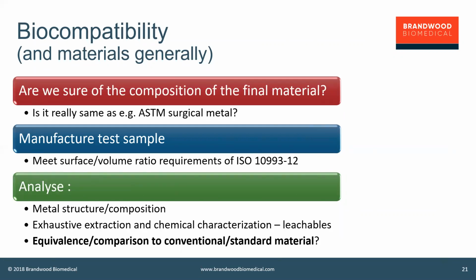And then you will take the solvent residue, analyze it and see what's in there, and then you'll do it again. And you keep doing that until the latest step has produced a residue which is less than 10% of the total. In other words, each cycle you do this, you'll get less out, and when the last step is less than 10% of the total, then you consider to be there. You've extracted more than 90% of what's extractable.